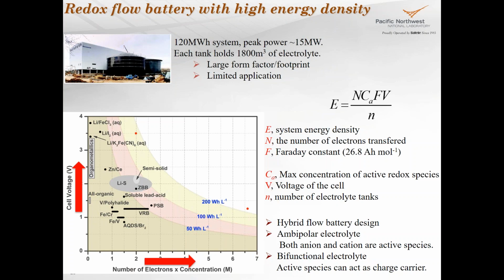You can see most of them are lower than 50 watt hour per liter, with some of the hybrid systems somewhere between 50 to 100 watt hour per liter. And for reference, most lithium ion batteries are higher than 200 watt hour per liter. So is it possible to make a redox flow battery with higher energy density? Apparently it's possible. We can do it in two ways. One is to increase the concentration, where we have a super high concentration of the electrolyte. Another way is to go into non-aqueous systems.